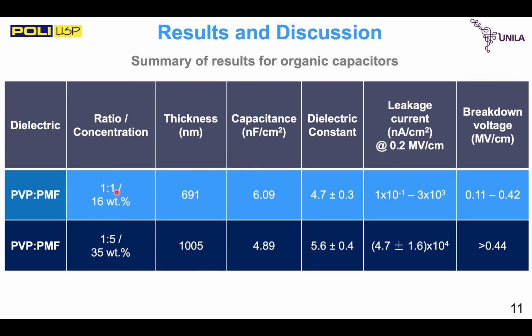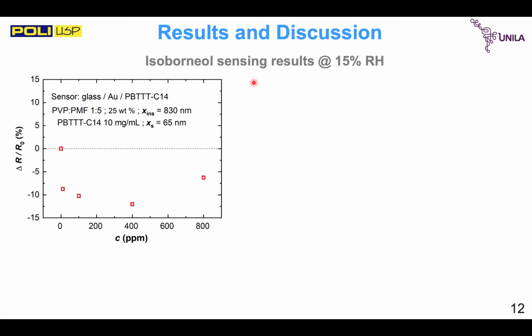Devices at 1 to 0, that means pure PVP capacitors, did not work, so did not withstand photolithography. And we could observe that devices with higher PMF ratio had higher dielectric constants, so high K devices, despite having a higher leakage current. However, this current was more uniform compared to devices with less PMF, and the breakdown voltage was also higher in this case. Okay, so after studying the capacitors, we studied the transistors, but also the chemical sensors.